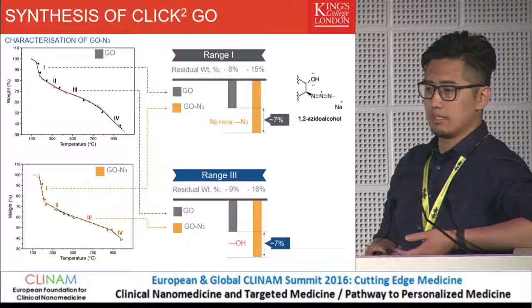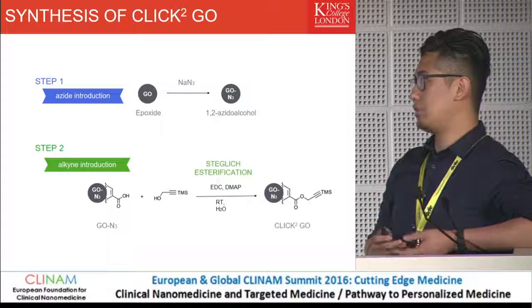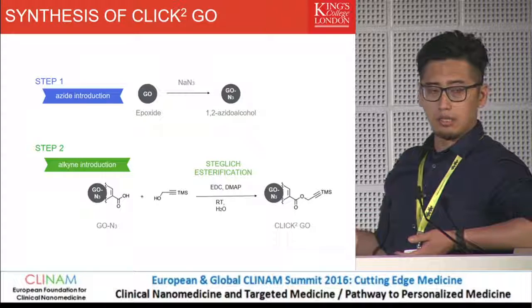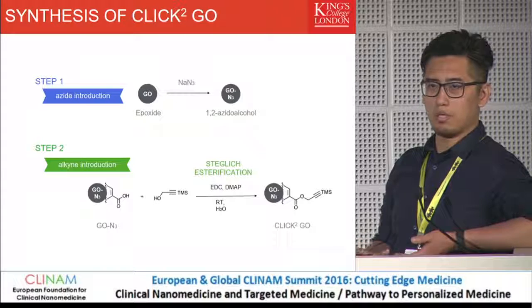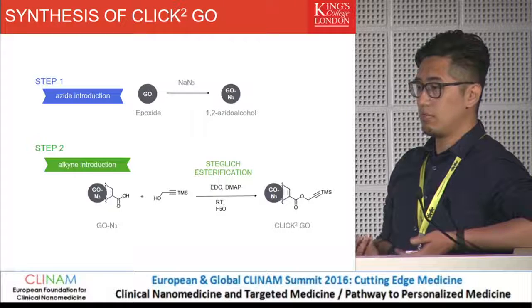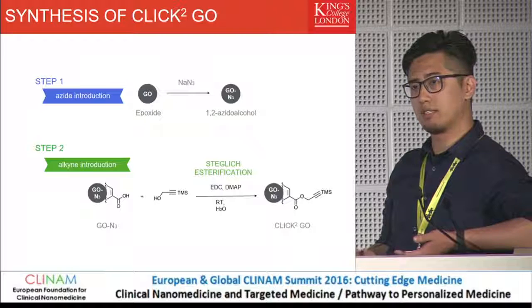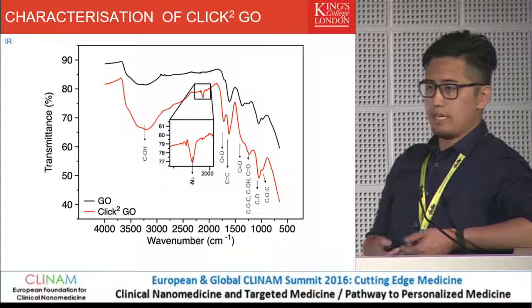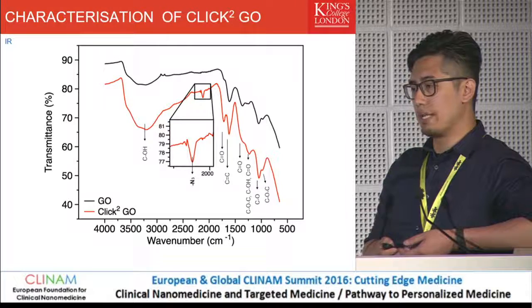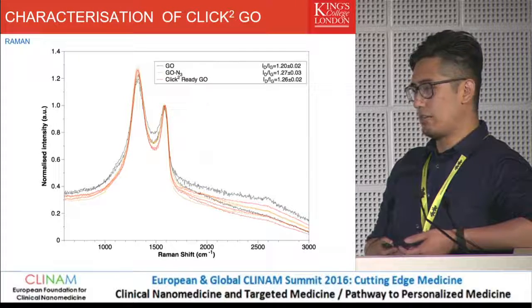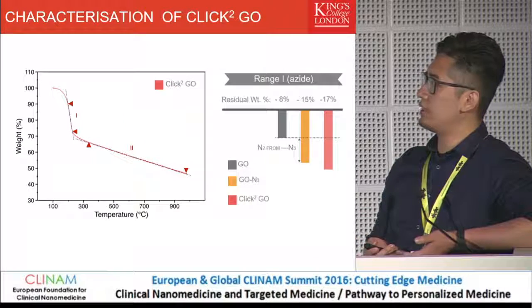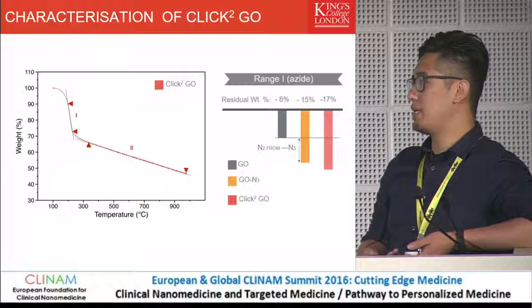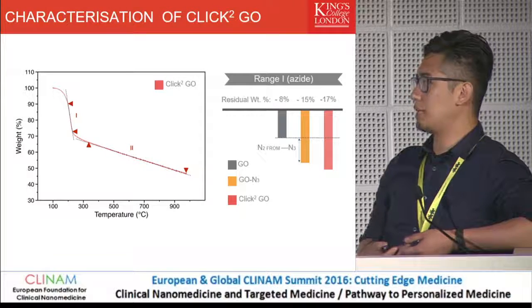The second step was to introduce the alkyne. What we use is TMS-protected propargyl alcohol, and we use EDC-type esterification to do conjugation on the carboxylic groups. This is actually a cleavable bond — an ester bond — so it can be cleaved under low pH. The material will not have the bond easily cleaved in a biological environment, but we want to see how the system behaves in this design. We check the IR, but alkyne doesn't have a strong IR signal, so you can't really see what's happening. For a small molecule with alkyne, you would have a strong Raman signal, but unfortunately it is obscured by the graphene. We can only see differences in the thermal decomposition profile — the decomposition ranges are reduced from four different ranges into two. It appears that conjugating or capping the carboxylic group with propargyl alcohol seems to stabilize the material.